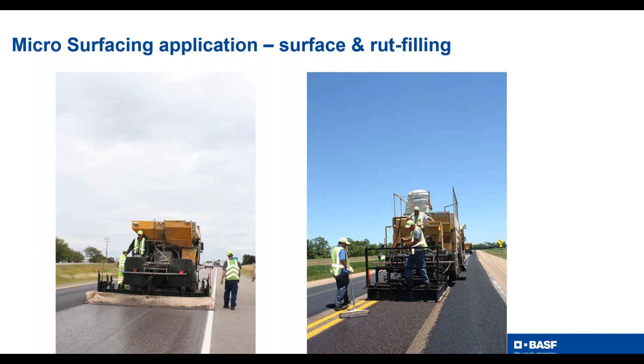The one on the left, they're using a burlap drag rather than a secondary strike off. There's some folks that still use those because of the texture that they want. The picture on the right shows a rut box in place where it's filling each wheel rut of the pavement in two separate passes. You notice the pass on the right, again, is much blacker in color, and it looks very good. The pass on the left is a little brown, and again, that will turn fairly black. Usually in rut filling applications, you'll see these two, and they'll actually put a surface over these rut fill applications as well. But sometimes they just leave the two rut fill applications, but that's not very often. But that's an important process too in microsurfacing.